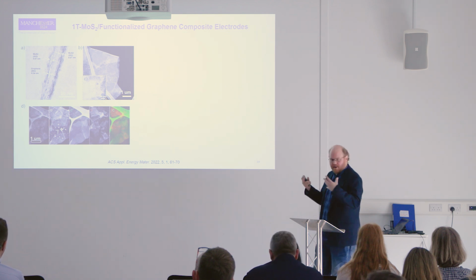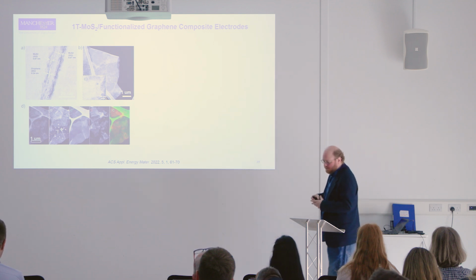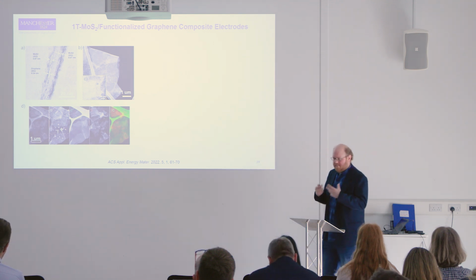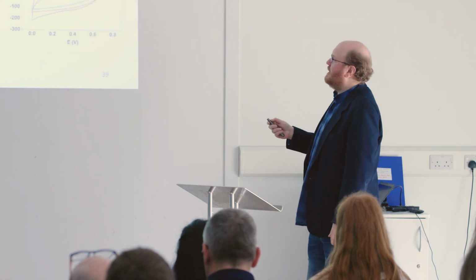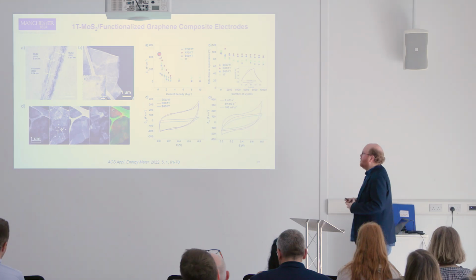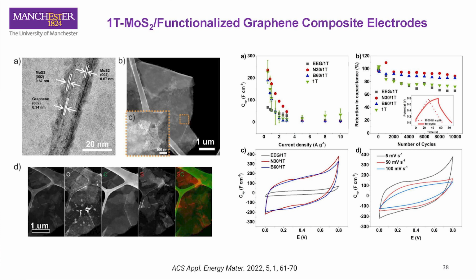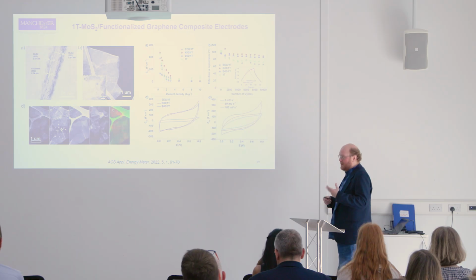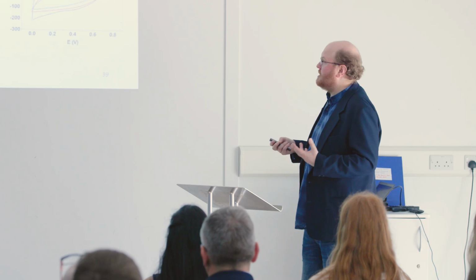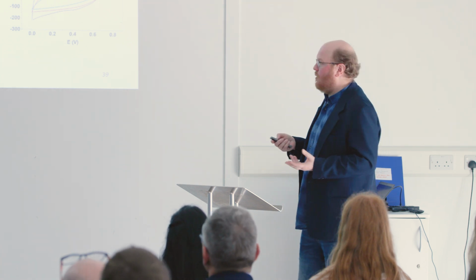And so that gives you a very nice high surface area where the MoS2, which is a semiconductor, has good capacity but is not very conductive. You've got this nice electrically conductive backbone in the form of the graphene. So that's why you get this synergistic benefit: the graphene and the MoS2 prevent the restacking, but you've got a highly conductive backbone. The capacitance of the composite structures is much, much higher than pure MoS2 or even pure graphene. That really shows the synergistic interaction is very beneficial for energy storage applications, and you can tune it and understand how that works better for whatever commercial application you need it for.